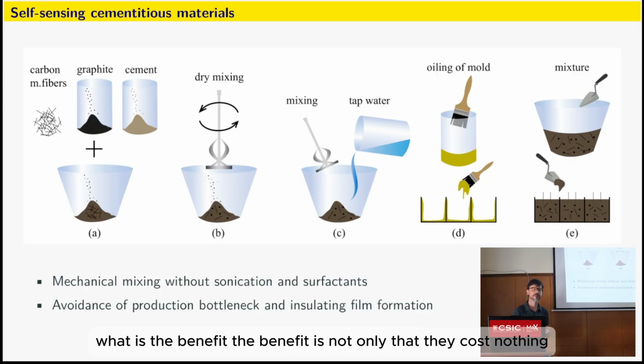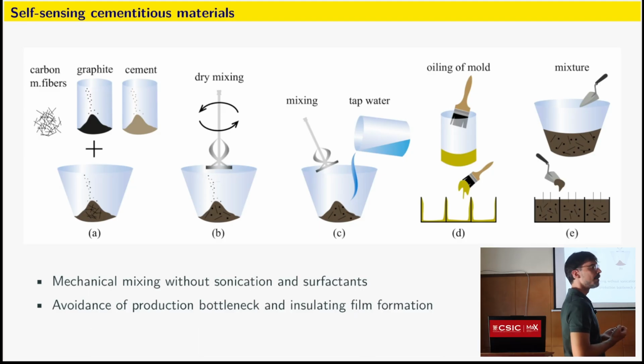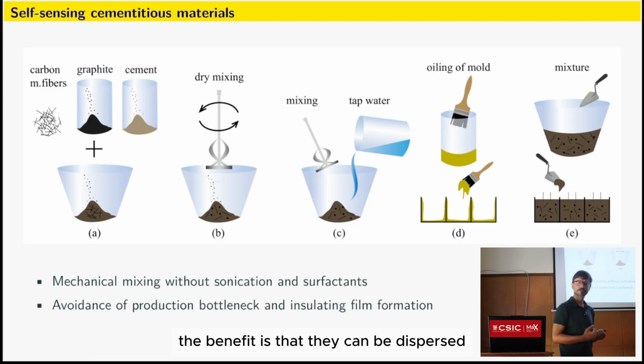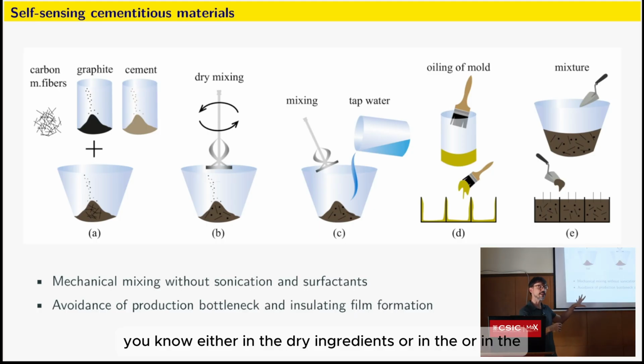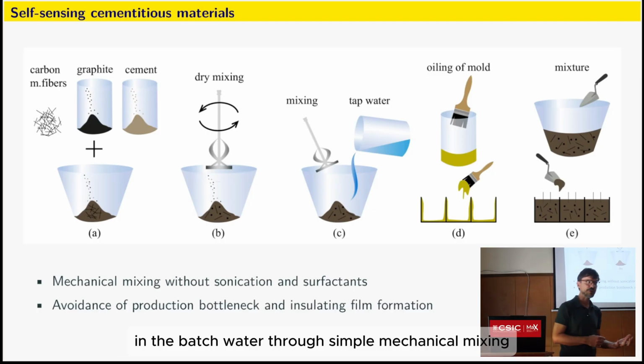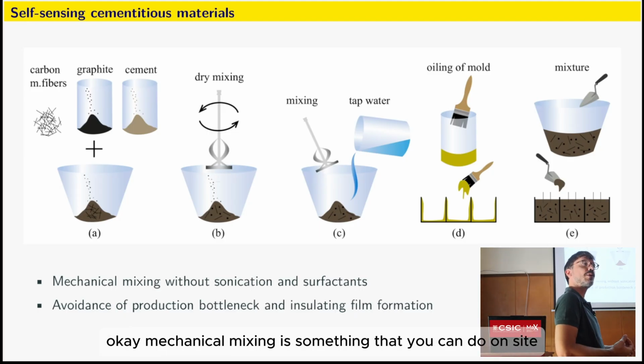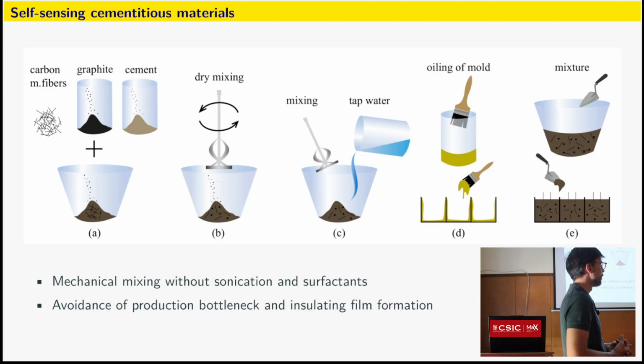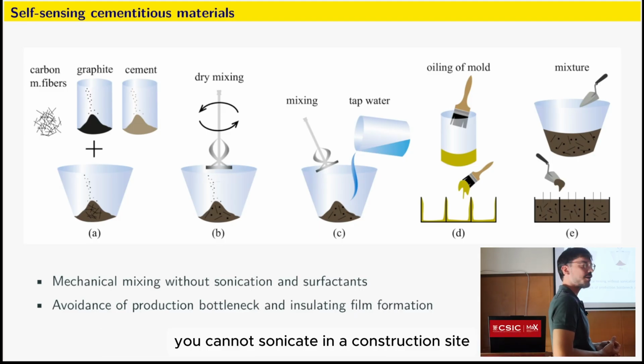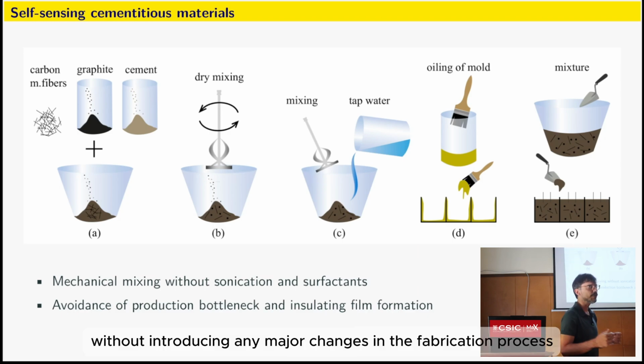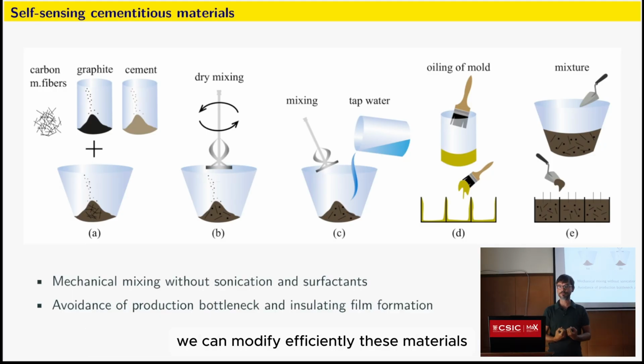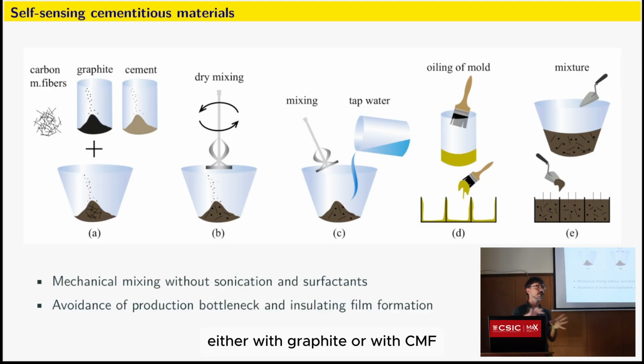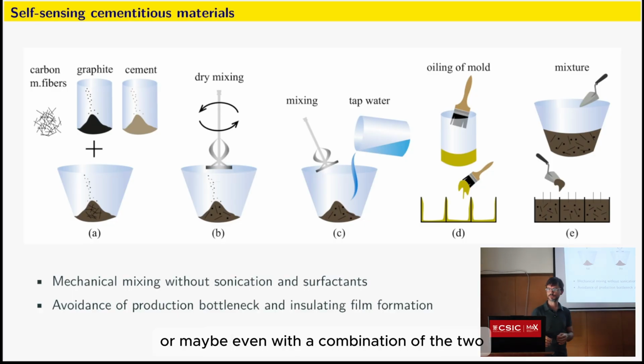Why? What is the benefit? The benefit is not only that they cost nothing and they are very easy to obtain. The benefit is that they can be dispersed, either in the dry ingredients or in the batch water, through simple mechanical mixing. Mechanical mixing is something that you can do on site of a construction. You cannot sonicate in a construction site. So really, without introducing any major changes in the fabrication process, we can modify these materials efficiently, either with graphite or with CMF, or maybe even with a combination of the two.